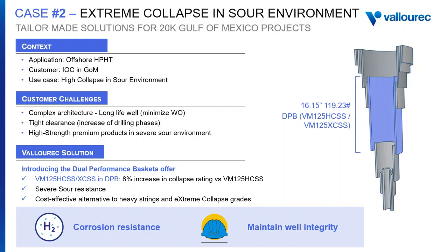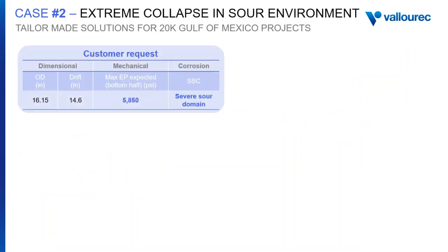The solution offered by Vallourec was a dual performance basket in VM125 HCSS grade that allowed an increase of 8% in the collapse rating while still maintaining the original well design. Let's focus first on the operator needs. A tubular combining a severe sour resistance with a minimum collapse resistance of 5,850 psi. It is important to mention that, in this case, the external pressure increased with the depth, and this elevated collapse resistance was needed only on the bottom half of the string.